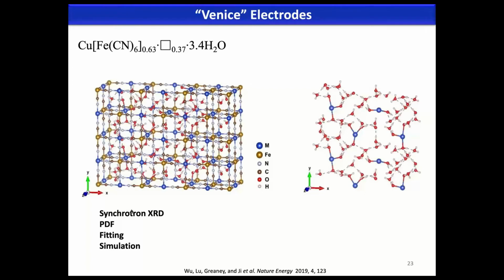Now, we need water to conduct protons, but in inorganic systems like metal oxide electrodes, phosphates or sulfides, you won't have water that rich enough to form some kind of Venice city structure for transportation. So we thought we probably need some reticular structure, a scaffold where we can put some water, but we don't want a really fluffy material to begin with. So we thought about the earliest version of MOF, which is Prussian blue.